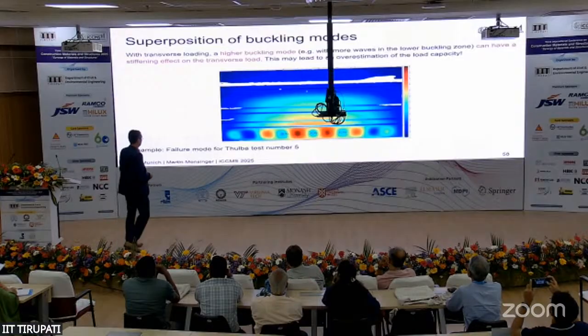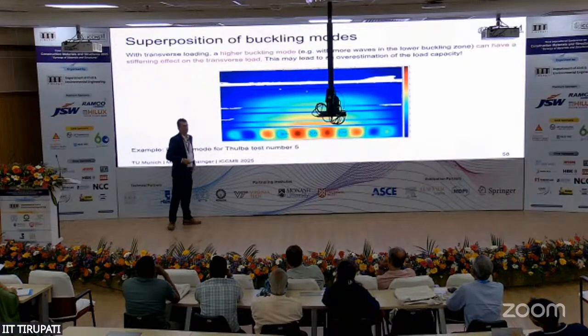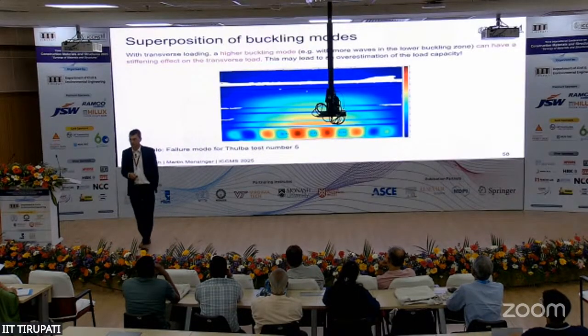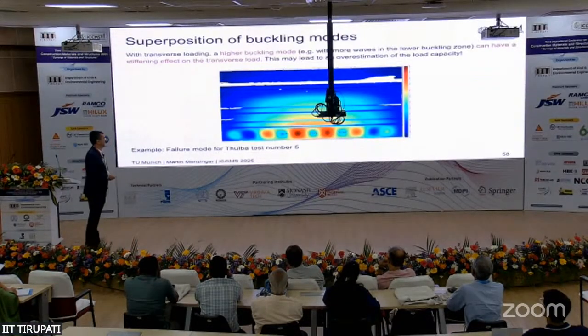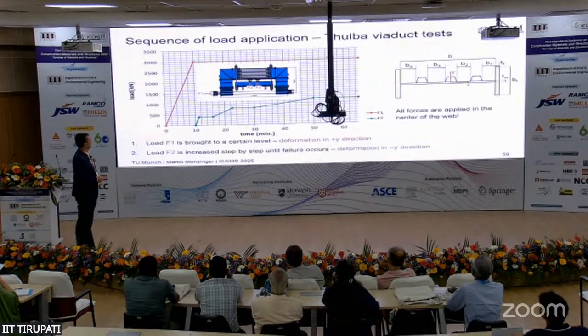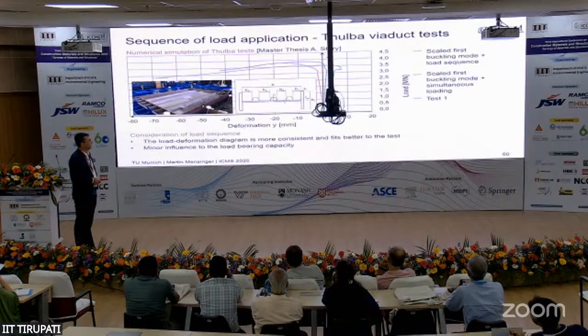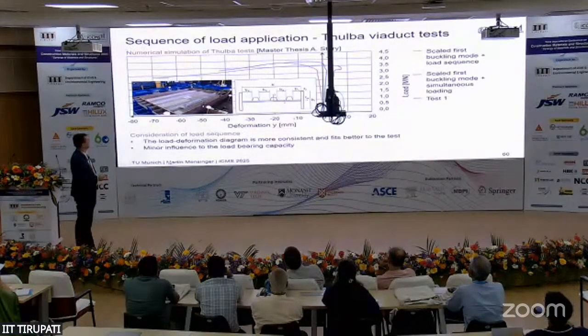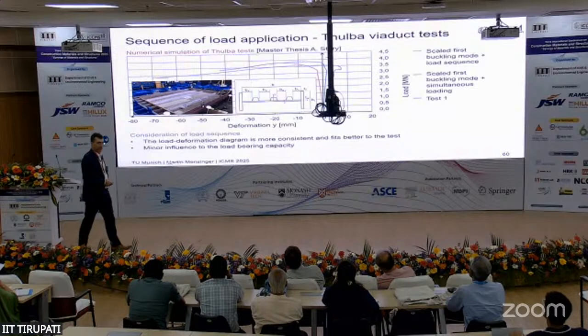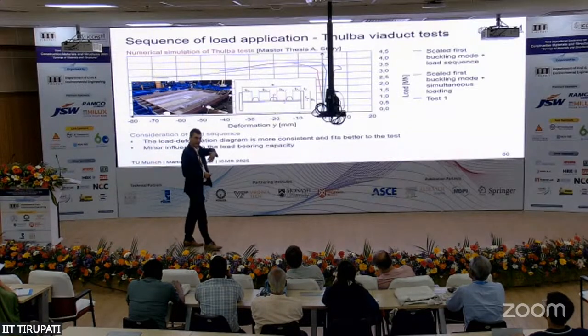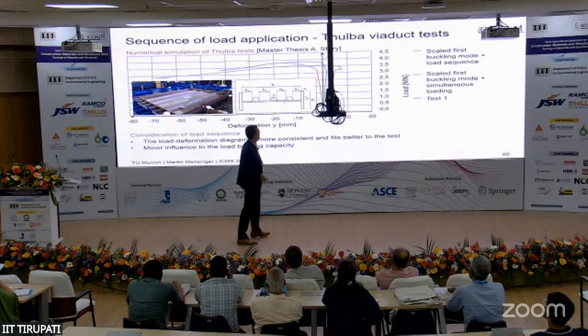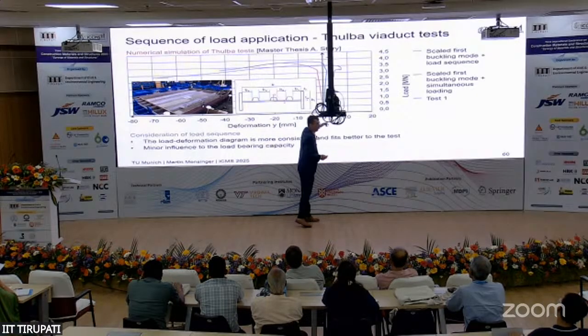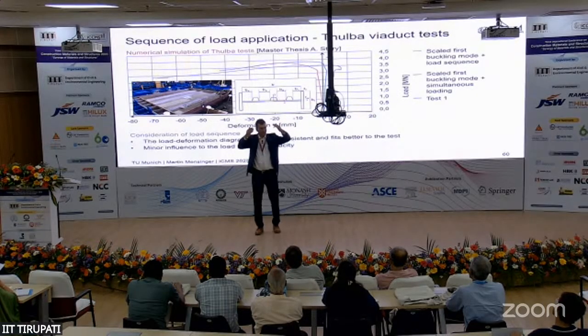And also, again, the effect I already explained, that we have this positive effect of multi-wave buckling in some cases. Then we were discussing the influence of the load sequence, and this was done by Alexander Stary, and we found out in that case that it has no influence on the ultimate load, but allows us a better understanding of the behavior of the test specimen during the test. So we had a change of the sign of the deflection. At the beginning, the test specimen moved down, and later on it moved up again.